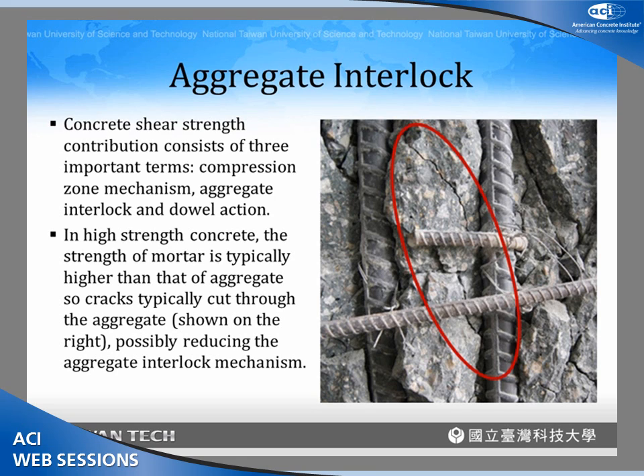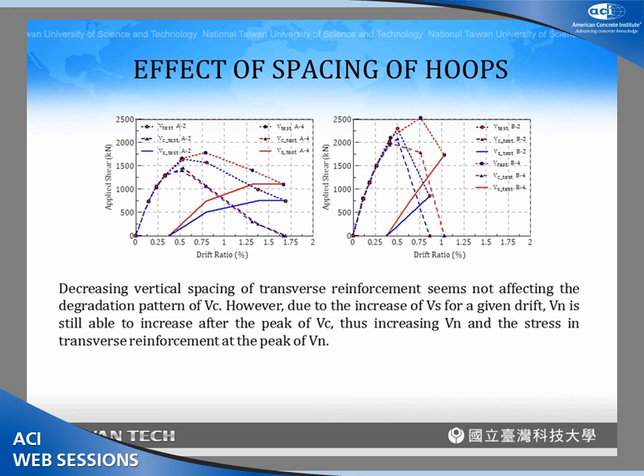And a possible reason for this phenomenon can be seen from this figure. This is a photo taken from the failure surface of one of the specimens, and you can see that the crack cut through the aggregate. When the strength of the concrete becomes higher, the strength of the mortar is maybe equal or even higher than the strength of the aggregate. So when you have a crack, the crack typically cuts through the aggregate. This will reduce the aggregate interlock mechanism in the concrete shear strength. So this reduces the drift at the peak concrete shear strength.